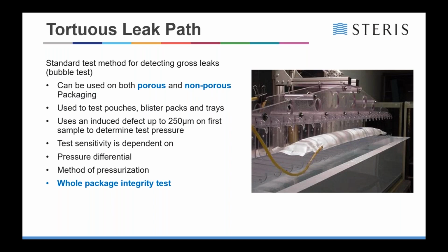So it not only tests your seals and your surfaces, but absolutely everything that you put the pouch through. So it will assess everything in any of the tests or any of the mechanical type tests that you've put it through previously. It can be done on either porous or non-porous packaging, and that includes the likes of Tyvek and paper. Paper can be extremely difficult to test depending on the grade of paper, and it is a very, very fast test again. It's used to test either pouches or blister packs and trays.